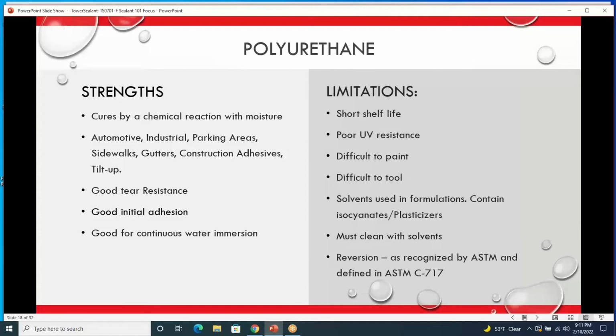It's used in automotive, industrial. You'll see it a lot in parking areas, sidewalks, gutters, construction adhesives, and tilt up. It has really good tear resistance compared to, say, silicone. It has great initial adhesion, and the big strength it has too is that it is good for continuous water immersion. So if you're using below grade, I would definitely recommend staying with polyurethanes inside a fountain or something like that. Look at polyurethanes. Limitations on it, though, it does have a very short shelf life.